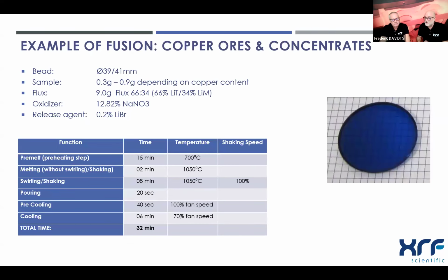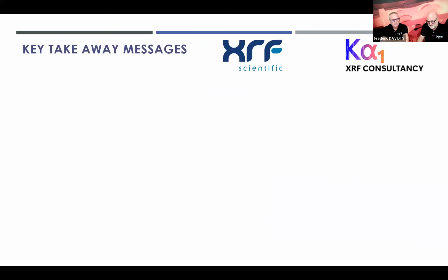And here is the case of a more severe or more complicated product to oxidize, and here again we put sodium nitrate in the flux, a little bit more quantity, but we let the machine do a 15 minute oxidation step at 700 to be sure that all the sulfide is oxidized into copper oxide, and that we can go, of course, to the next fusion cycle. And of course it's a little bit longer, it's 32 minutes in this case.